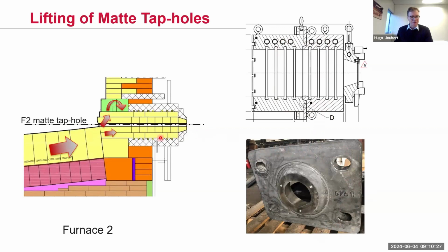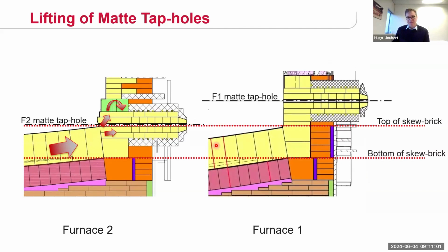One of the issues that we had with the tapping design on furnace number 2 is the fact that your tap hole sits in your skew back, basically. So the tap hole center line is in line with the top of the skew backs or skew bricks. As a result, any thermal expansion in your hearth impacted directly onto your mat tap hole, and that caused distortion of the mat tap hole bricks and the mat tap hole itself, as well as distortion of the very key lintels above the mat tap hole. So what we did for furnace number 1 is we lifted this mat tap hole completely out and above the skew brick area.